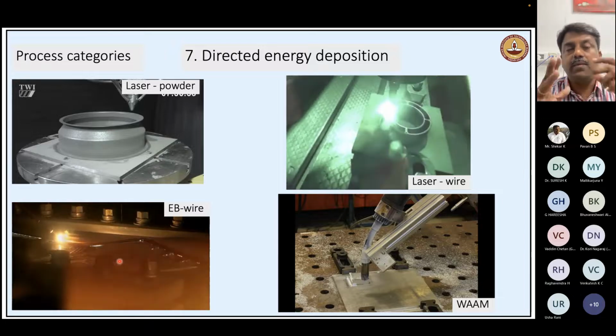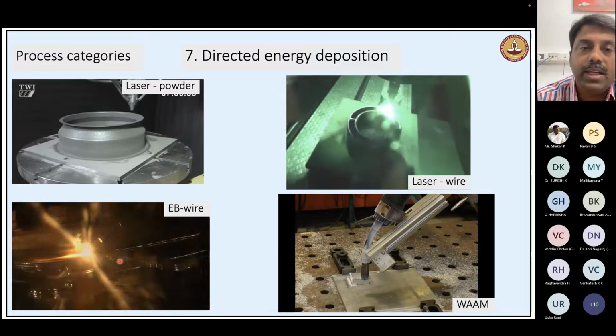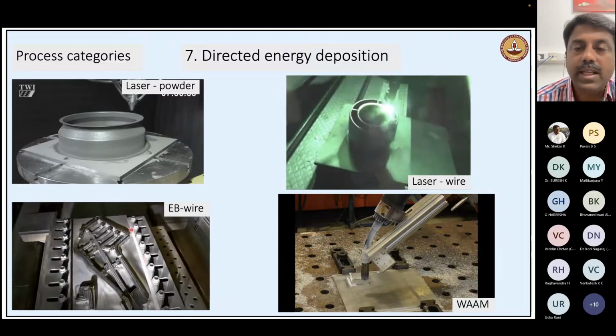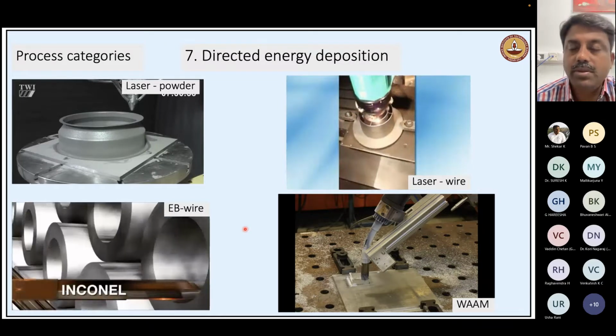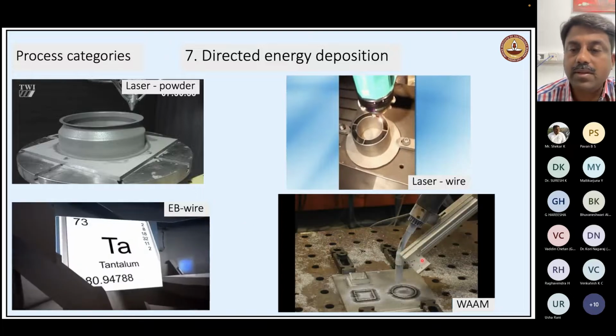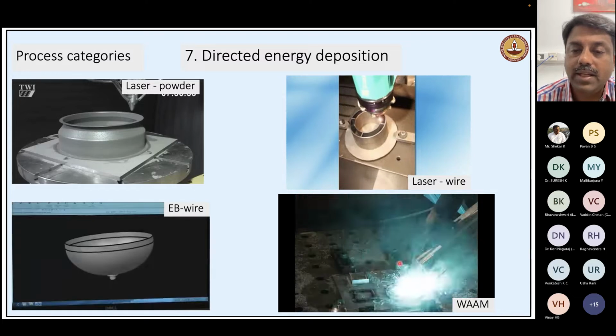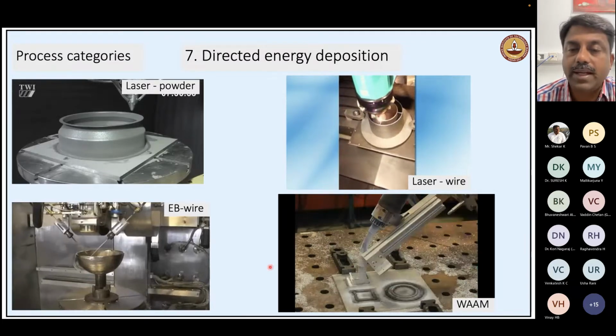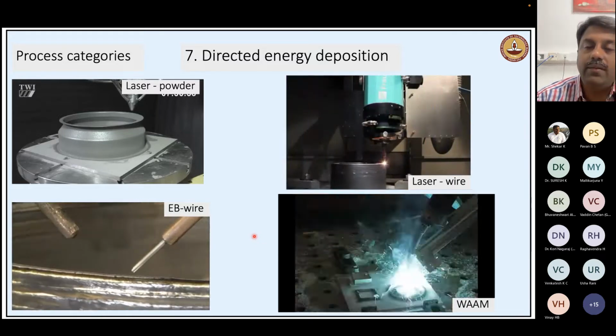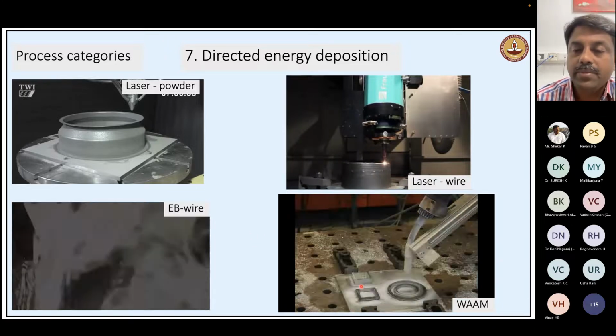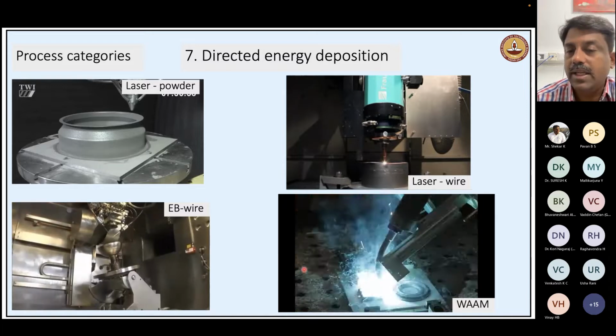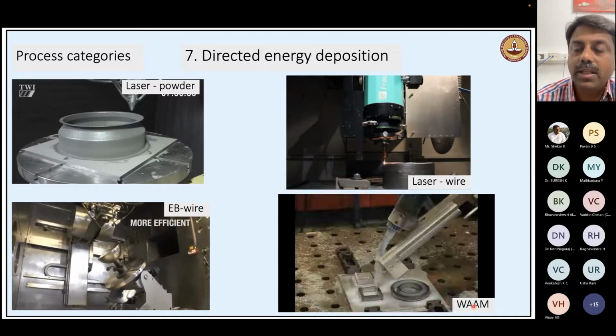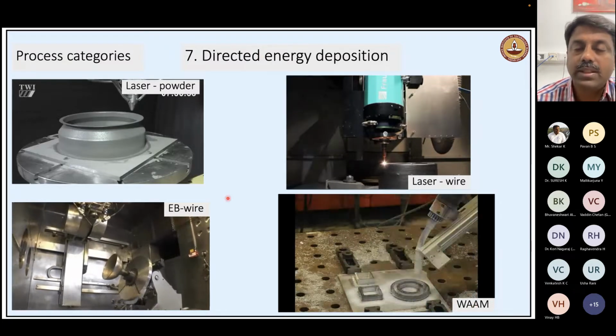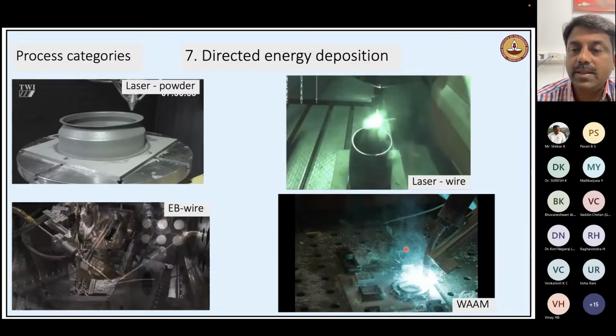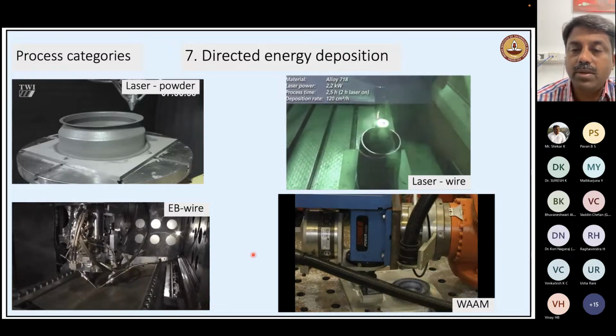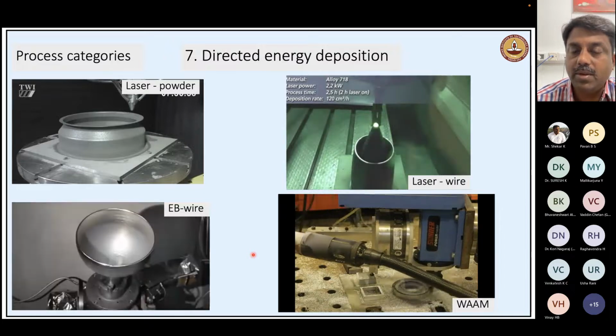The advantage of using electron beam is that we do the entire activity in a vacuum chamber, so very sensitive material can also be printed using this process, and it is highly energy efficient compared to laser. We can also use a simple welding setup. This welding setup has a gas metal arc welding torch, and we deposit layer by layer, and subsequently we can also use a machining tool to finish the already deposited layer. People also call this wire arc additive manufacturing, but the actual term is a DED process using arc plasma, so it's an arc wire DED process. What you see here is one of the setups we have, which can combine both deposition and machining together.